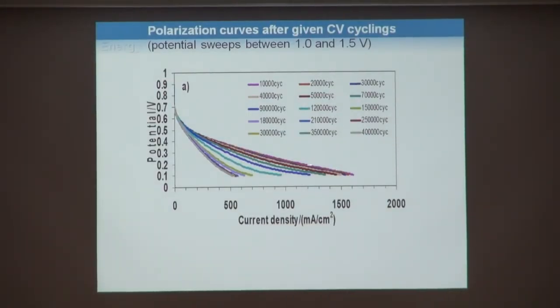So the pink one is after 10,000 cycles. And even after 10,000 cycling, the performance is almost similar to the original level. And after additional potential cycling, 40,000, 90,000, and finally 400,000 here. So it's amazing, but even after 400,000 cycling, our fuel cell is still alive like this. So this level is not very bad compared to this one, and the performance has decreased, but it is still alive. So that's a remarkable result.